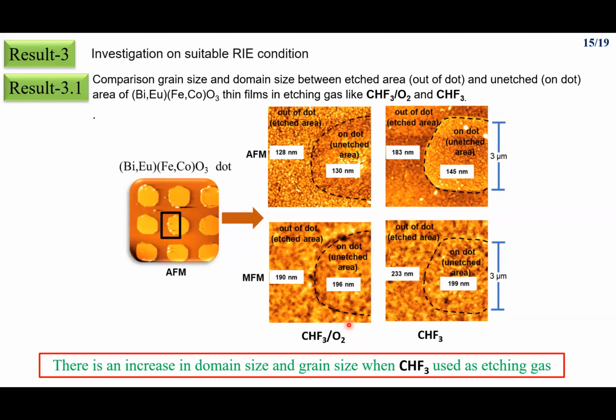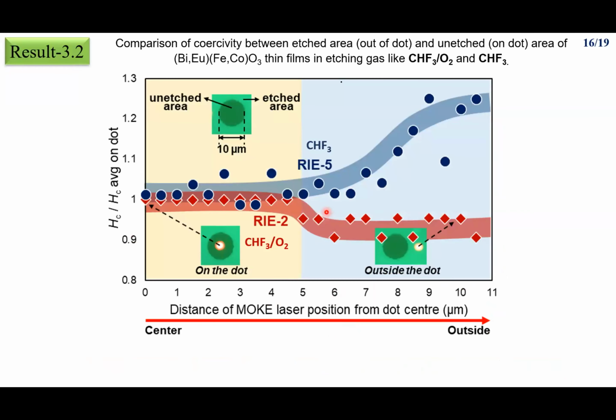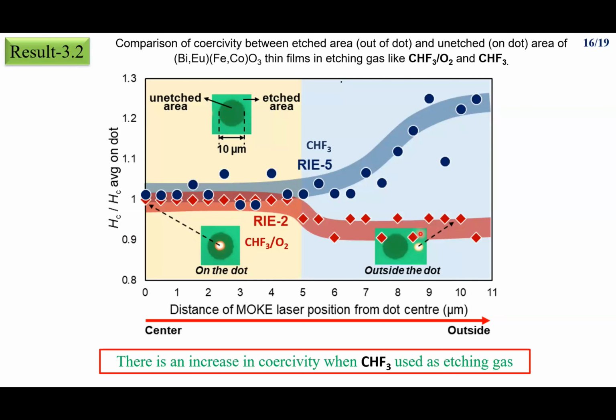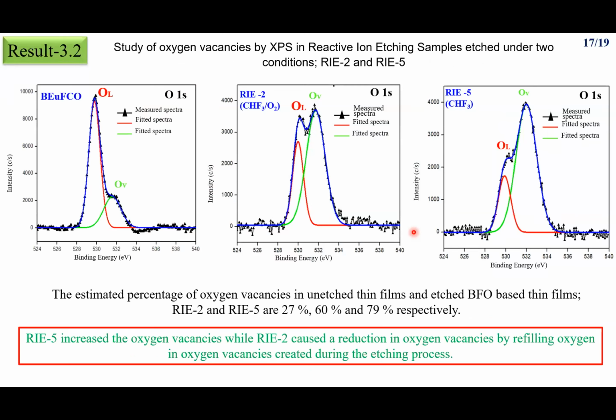That means in the presence of oxygen, the etching process is good. To confirm it again I checked the change in coercivity, and I found when there is etching in the absence of oxygen, this is giving a huge change in the magnetic property, but in the presence of oxygen, there is almost no change in the magnetic property. To confirm this, I did an XPS study to study the oxygen vacancy. In the bare material, when there is no etching, the oxygen vacancy is 27%, and in the presence of oxygen, it is giving oxygen vacancy of 60%, and in the absence of oxygen, it is giving very high oxygen vacancy, that is 79%.